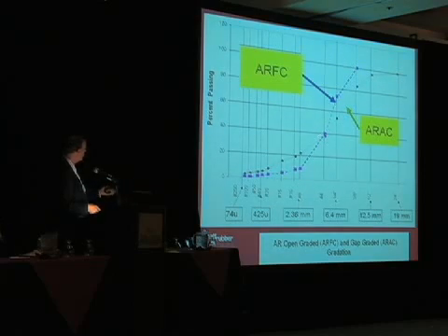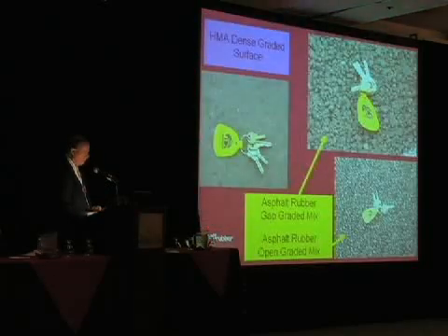You notice this grading here, which is the gap graded or coarse graded, very much like an SMA type gradation, and you can see the 2.36 or number 8 is down around 20-some percent, which is like an SMA, just without very high 200s. And then the open graded is pretty much a one-size chip. You'll see a picture of that a little later on.